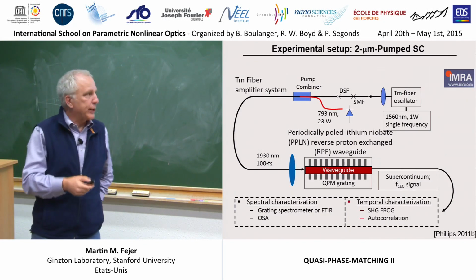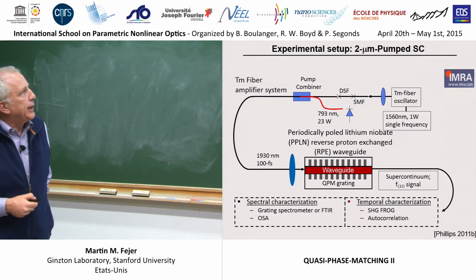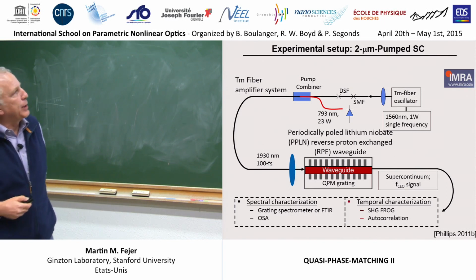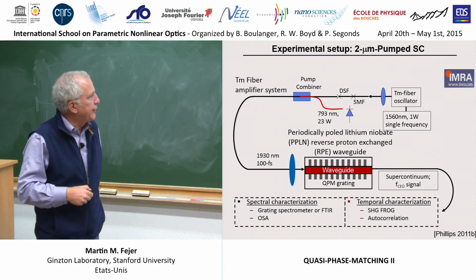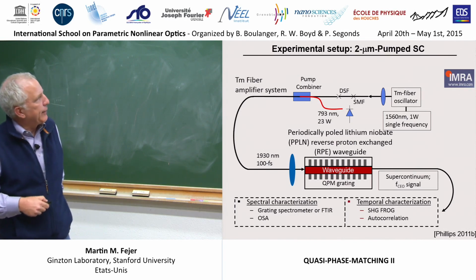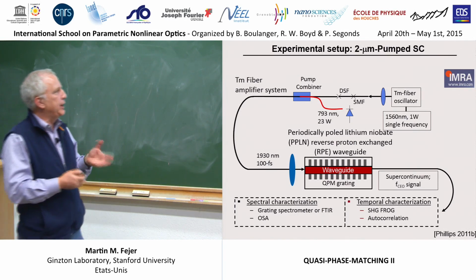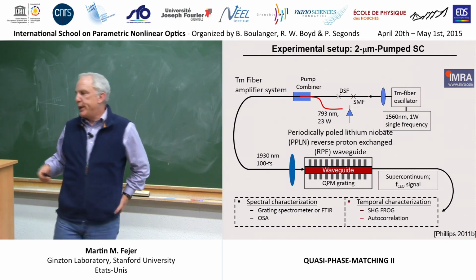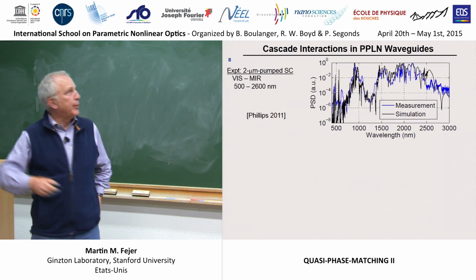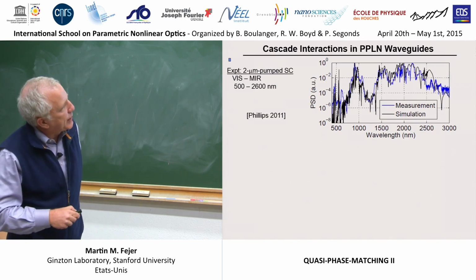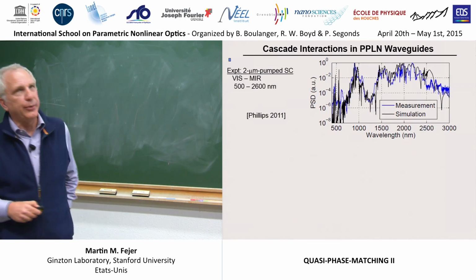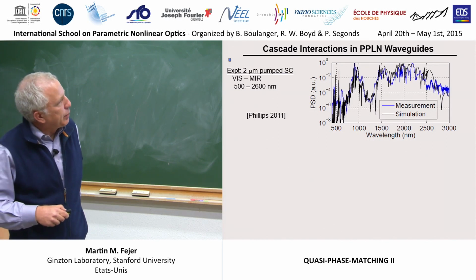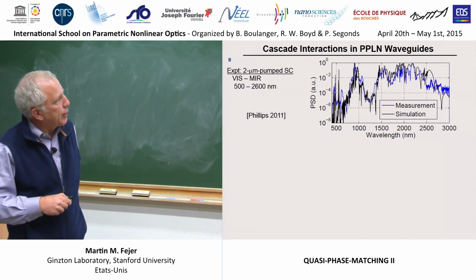So one last quick look. Chris tried a 2-micron pumped supercontinuum generation with 100 femtosecond pulses from a thulium fiber laser in the vicinity of 1.9 microns. And this is really remarkable. This continuum extends from 500 nanometers to 3 microns. And the black line is the simulation with no free parameters in it.